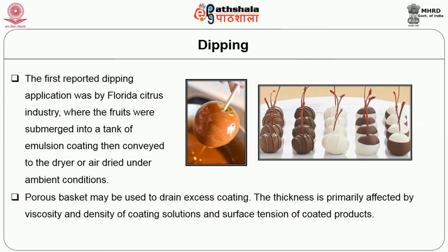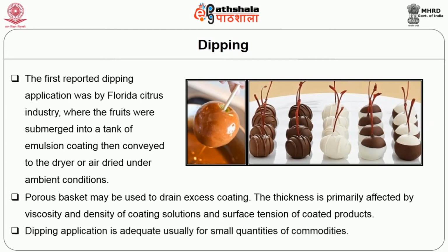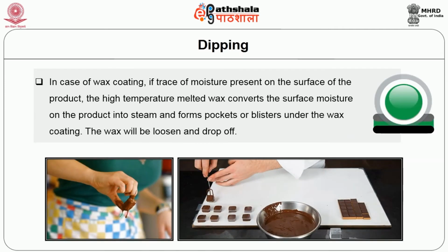Porous basket may be used to drain excess coating. The thickness is primarily affected by viscosity and density of coating solutions and surface tension of coated products. Dipping application is adequate usually for small quantities of commodities. Before coating, the surface must be clean and moisture free. In case of wax coating, if trace of moisture present on the surface of the product, the high temperature melted wax converts the surface moisture on the product into steam and forms pockets and blisters under the wax coating. This wax will be loosened and drop off.